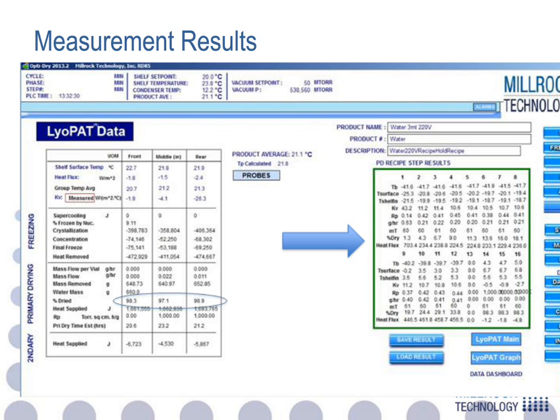You'll notice the KV in this particular one is all over the place because the thermocouples are out of the product, so the KV is meaningless. But this is some of the saved data. During freezing, we actually calculate the amount that would be frozen by nucleation. We calculate or measure the energy that was taken out during each of the freezing steps. And then during primary drying, we calculate the mass flow per vial, the mass flow for the batch, the mass removed. Obviously, we know the total mass. We calculate the percent dried.